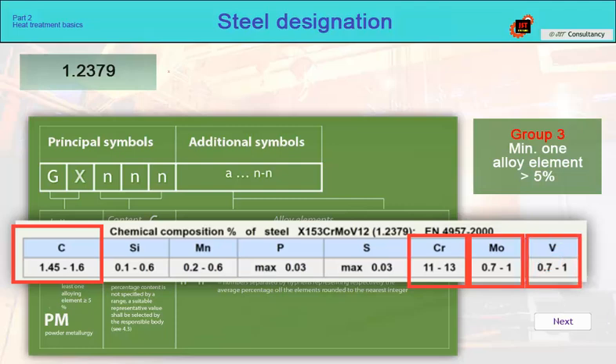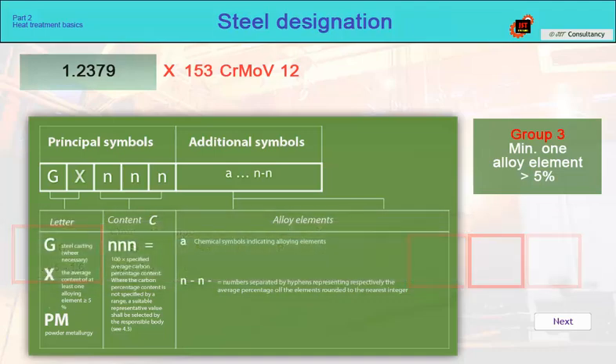The steel designation will therefore begin with the letter X. 100 times the carbon content is expressed by the number 153. The alloying elements, chromium, molybdenum, and vanadium, are then listed. And finally, a number must be added expressing the alloy content in percent. In the case of chromium, this is 12%. Other alloys are up to 1%, and therefore their number will not be indicated. The final steel designation will therefore be X153 chromium molybdenum vanadium 12.